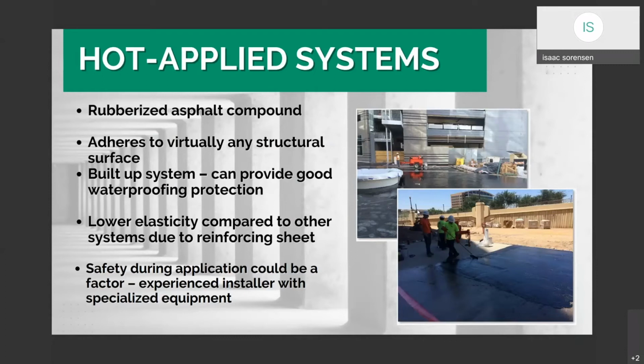Because of the reinforcing fabric, the elasticity of this product can be a little lower than some of the others. Because it's hot, you have to be very careful, of course. The best, of course, is to have it applied by a certified specialist. Reinforcing is added to allow a second layer to become integral with the first. And more importantly, the second layer was used to address pinholing that was seen occurring early on in the use of this type of membrane system,